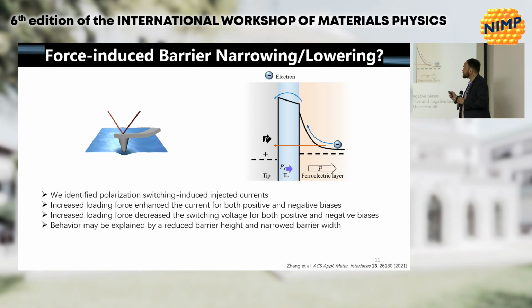Okay, so in this part of the work, we identified polarization switching induced currents. We observed an increased loading force and that enhanced the current for both positive and negative biases. And this increased loading force decreased the switching voltage for both positive and negative. And what we think might be happening is that when we're applying this force, we're actually squeezing, we're pinching that dead layer. And in doing so, that allows for the enhancement of the tunneling current, but it also perhaps reduces the barrier a little bit. So some combination of those effects is giving rise to this enhanced current, which is orders of magnitude higher than could be possible just from switching bismuth ferrite.